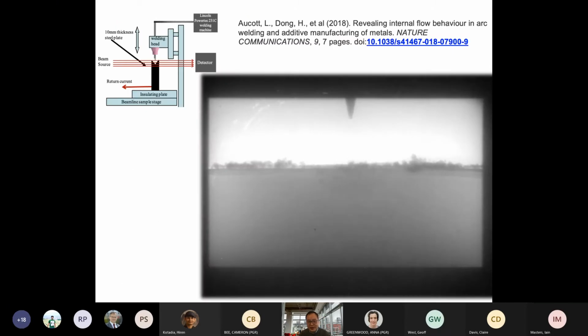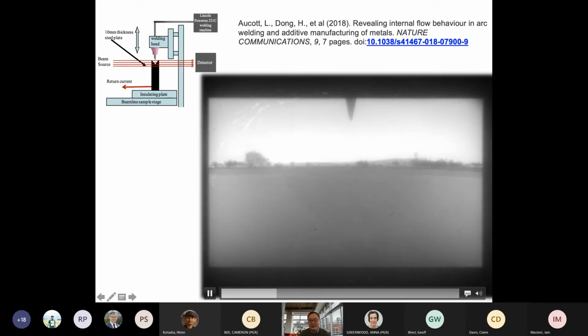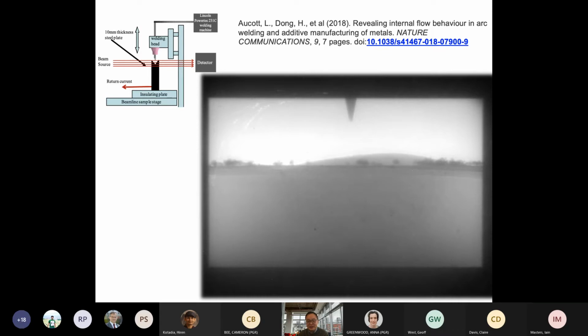So this is our experiment, and this is what it looks like. I think the overall length is about 10 millimeters. This view window is about 10 millimeters. Now you should be able to see the arc gun at the top, and then you have what we call the free surface of the liquid metal moving up and down. After melting, this will be the melt pool, and you see those black particles inside. These black particles are tungsten particles. Because tungsten particles absorb a little bit more X-ray, you will see them a bit darker. So this is the raw image.